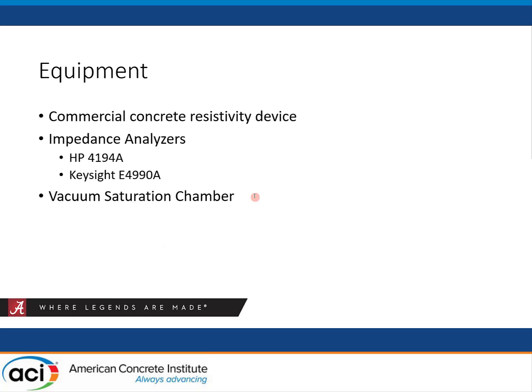And so we did this with several pieces of equipment. We have a commercially available concrete resistivity device. We have several impedance analyzers available in our lab. We have an older HP 4194A impedance analyzer, and then a much more modern Keysight E4990A impedance analyzer. And we're in the process of acquiring a Solartron impedance analyzer to round out this part of the study. And we also have a vacuum saturation chamber so that we can ensure we get all of our mixes into what we would hope is a near 100% saturated state for that final reading.